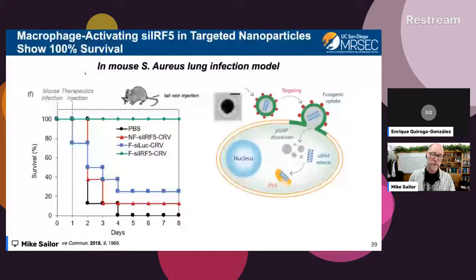And if we don't use a fusogenic lipid, but we use the same targeting peptide, it's effective, but not nearly as effective as using this fusogenic coating. So again, it shows how important it is to avoid that endosomal uptake with nanoparticles.